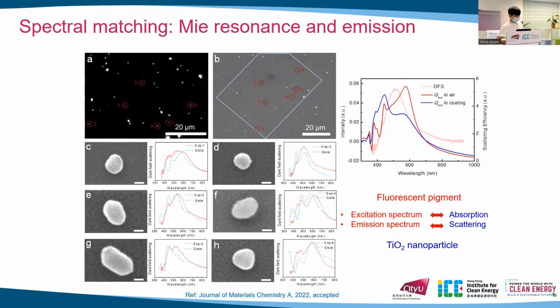There are two dielectric environments, the top air and the bottom glass. Both of them have a refractive index smaller than the coating. According to this theory, a larger refractive index of the surrounding medium will red shift the scattering peak.